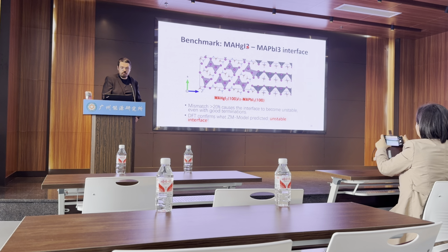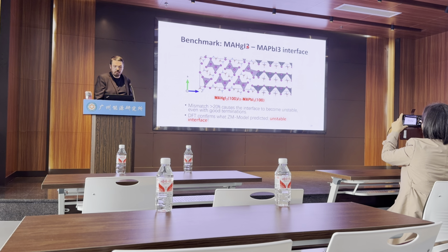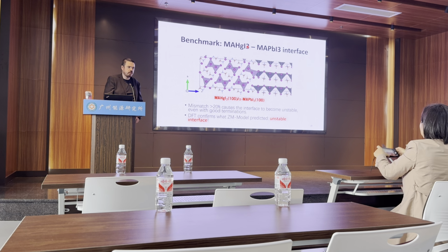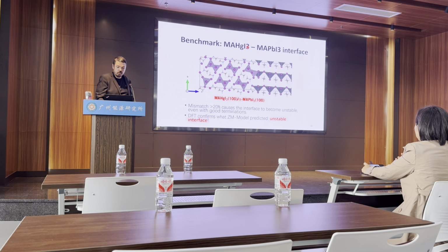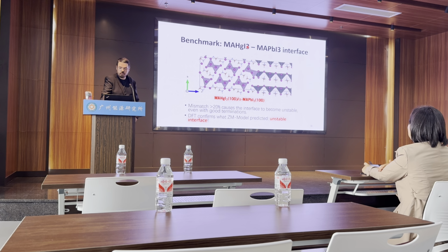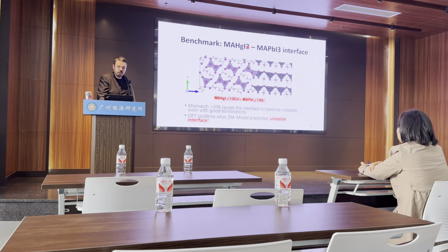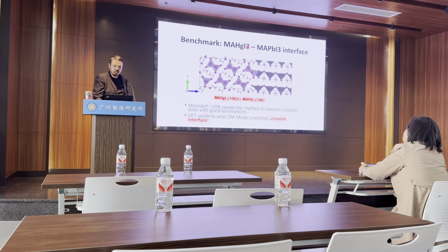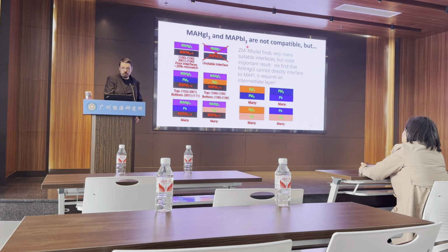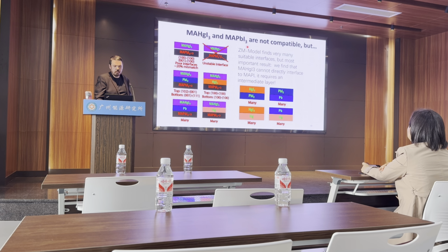But first of all, the mismatch is over 20% as the ZM model predicted, and ultimately DFT says it's unstable. So the ZM model is actually reliable to some degree, I suppose, but in this case it's very reliable. So we had to find an alternative explanation. We can't have the perovskite type HG phase, no good.